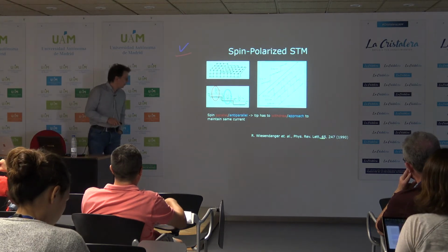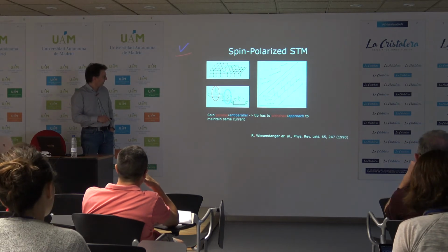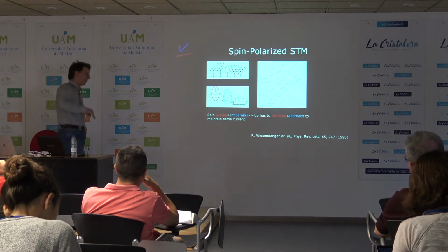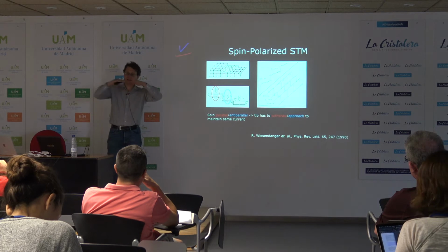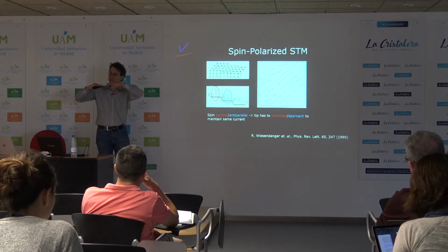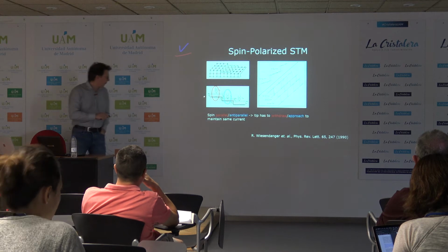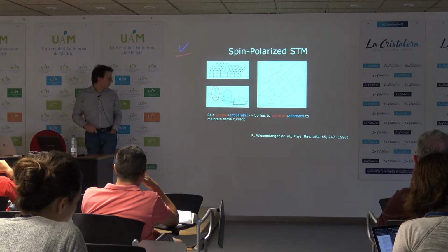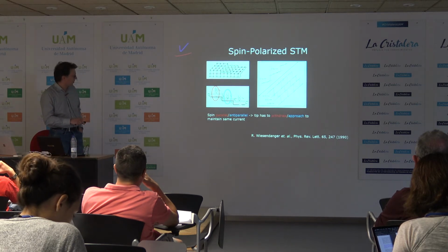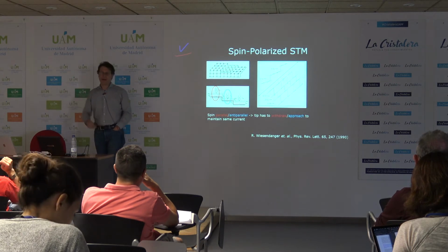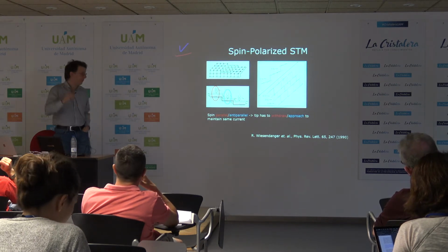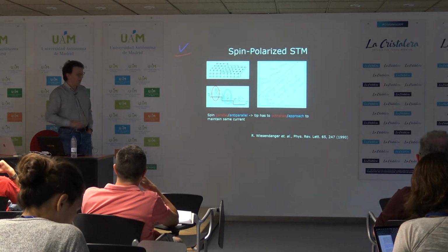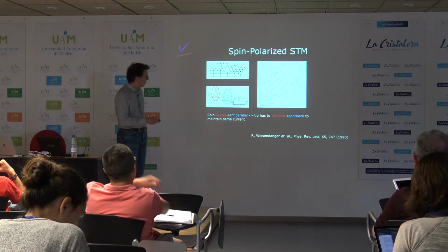So he used an antiferromagnetic tip and studied a chromium 001 surface where you have ferromagnetic layers but alternating with opposite spin direction between adjacent layers. So if you look at adjacent terraces, they have opposite spin, but within the terrace, the spins are in the same orientation. And now if you use a magnetic tip to scan across step edges, then you detect different step heights depending on whether you move from a terrace where the spins are parallel to one where they are anti-parallel, or the other way around. And this is showing his measurement here.